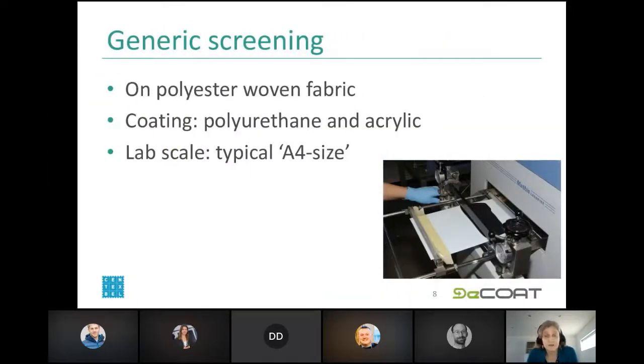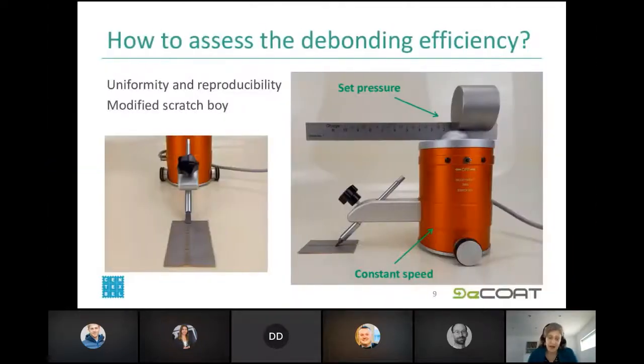So we start in the project with the generic screening. We just took a simple polyester woven fabric and we coat it with some standard textile binders, polyurethane and acrylic ones. And we're just producing A4 size typical lab scale samples. The first problem we encountered, actually, was how can we assess the efficiency of the different triggers?